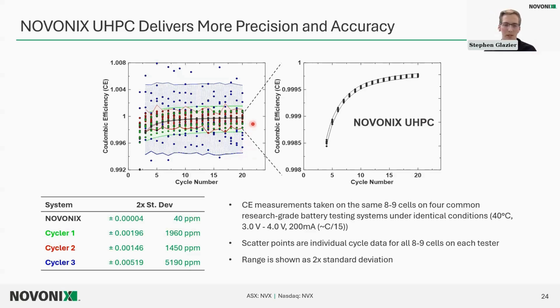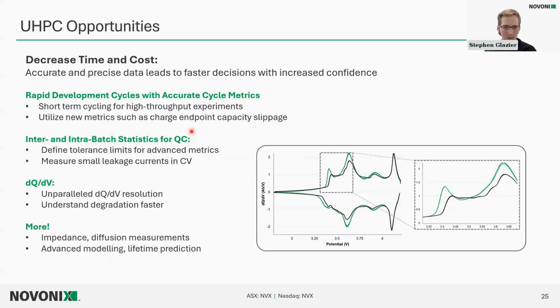So if you're doing quick iterative work and trying to look at new formulations of electrolyte, or do vendor selection on cathode materials and understand which material is more electrochemically stable, or how do these perform at these different operating conditions, the UHPC is going to be able to tell you that in just a few cycles rather than waiting months for these trends to appear. So this can be done by cycling cells and using really accurate cycle metrics to look at trends very quickly.